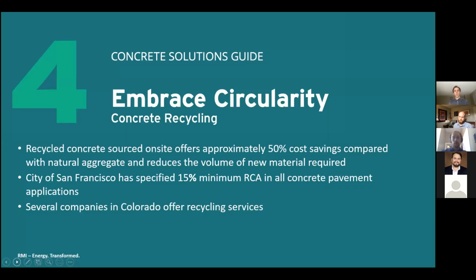is the third solution, which is around concrete recycling. So as I mentioned earlier, concrete recycling has a smaller impact in terms of emissions because it's offsetting new aggregate rather than any of the cement, which is where most of the embodied emissions are coming from in a given concrete mix. But it does have some other benefits. So if it's used on site, it can offer cost benefits. If it's used on the same site where it's produced, often those cost benefits are negated once the material has to be transported any significant distance. And obviously it avoids the waste stream that would otherwise be in place.